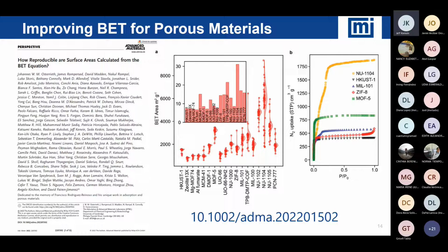If you move to the right side and you look at the materials that start with the prefix NU, these are from Northwestern University, and these Northwestern University materials are hierarchical metal organic frameworks. So they have 3 very well-defined pore systems in those materials. You notice that there's a very broad range for the reported surface areas. So for all the researchers that received these, they all calculated different surface areas from the same isotherm. Right? You see surface areas as low as 2,000 meters squared per gram to surface areas exceeding almost 9,000 meters squared per gram. And this is one of the concerns now for researchers.